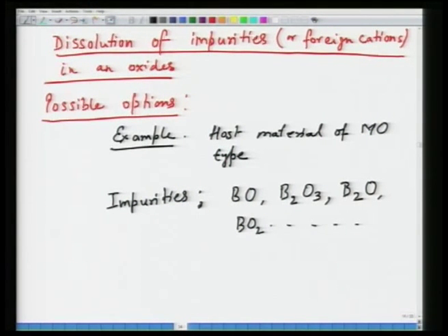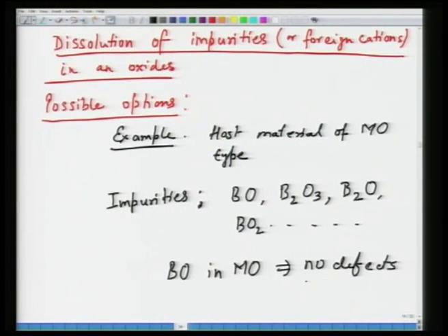Now, if it is a substitutional impurity, which means B replaces M on the metal side, in that case you do not have any problem. Oxygen occupies the oxygen side and B occupies the metal side, given that their sizes are not too different. If the sizes were too different, then the host lattice does not accept the impurity that readily. As a result, the impurity is present as a solid chunk inside the material rather than substituting, because it gives rise to massive strain in the lattice. However, if the sizes were equivalent, then BO in MO gives no defects, because the valence of B and the valence of M are equal.